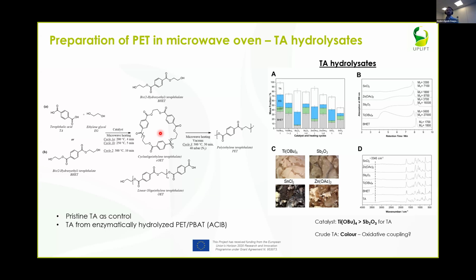Very often antimony catalysts are used for these polymerizations, and it would be highly attractive if we can transition that into, for instance, titanium catalysts or zinc catalysts instead of the tin catalysts that are also often used as an alternative here. I don't want to go into the details of the different systems, but what you can see is that we can investigate different catalysts, and we can see how that affects the distribution of the different products. If we go out here on the right-hand side, this is the size exclusion chromatography that you can see. And what is very interesting here for the hydrolysates is that the titanium catalyst is actually superior in making new polymers compared to the industry standard, which is the antimony catalyst.